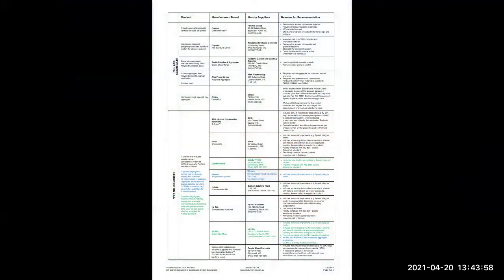So by referring to the Mullum Creek Concrete and Cement Products Guide, you can find out who batches concrete with SCMs. ACM Ecrete and Wagner's EFC, they contain geopolymers that activate SCMs to avoid the use of Portland cement altogether. And a number of the suppliers listed also blend crushed concrete in with the aggregate mix, certainly for lower MPa mixes, and they can source coarse aggregate crushed from rock that's removed from excavations on construction sites. All these initiatives lower the embodied carbon and biodiversity impacts of wet mix concrete significantly.